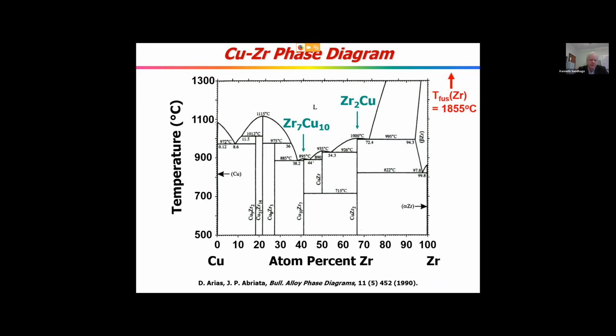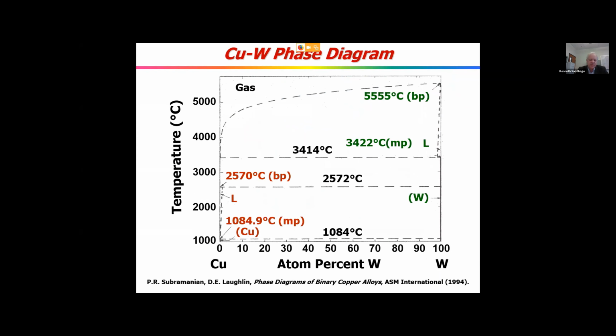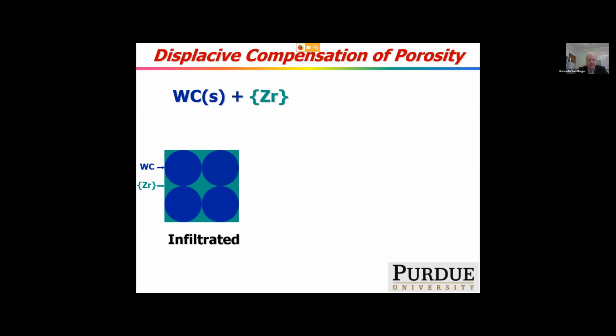What's more, copper is inert with respect to zirconium carbide and with respect to tungsten. Here's the copper-tungsten binary constitution phase diagram. Probably the most boring phase diagram you'll ever see. They don't form any compounds together, with very limited solubility in each other. And what's more, the melting point of tungsten, 3422 C, hardly changes in the presence of copper, 3414 C. And I suspect much of that difference could be the error of the pyrometer used to make these measurements. So it's a very negligible interaction of copper with tungsten as well. So it's an excellent solvent for this application.